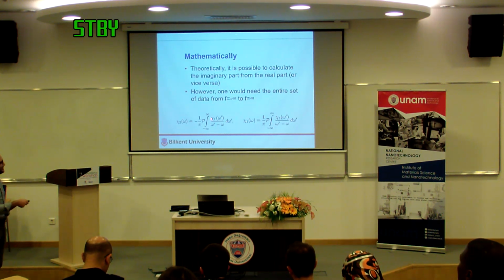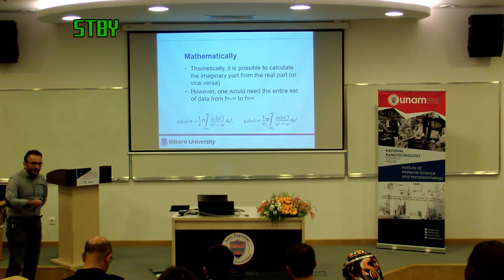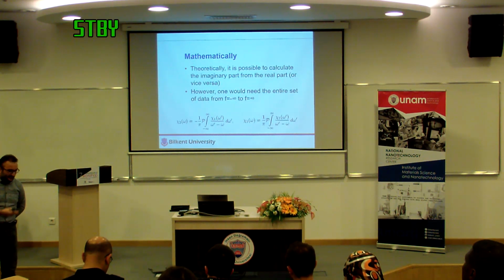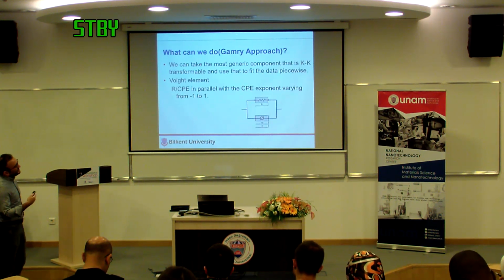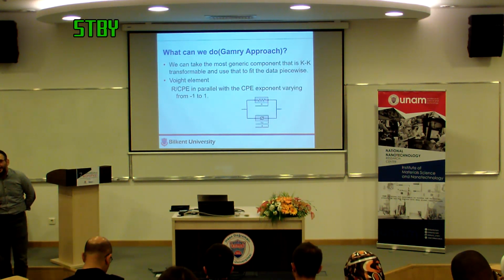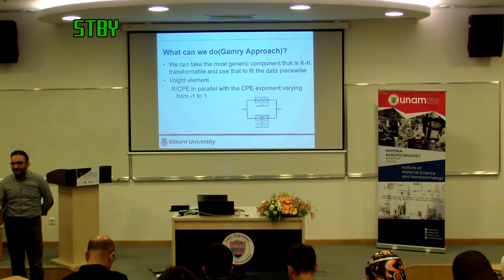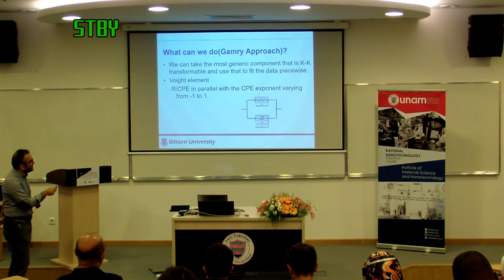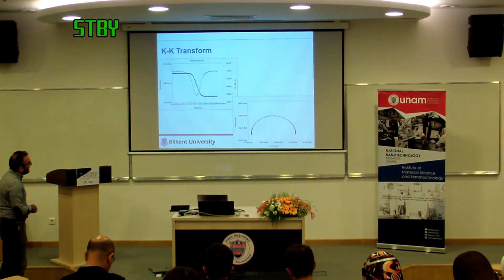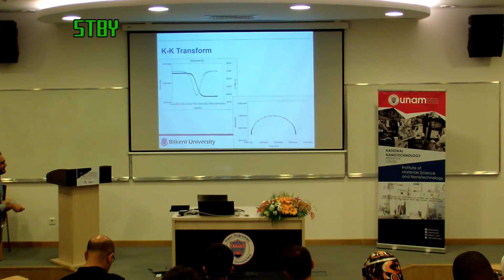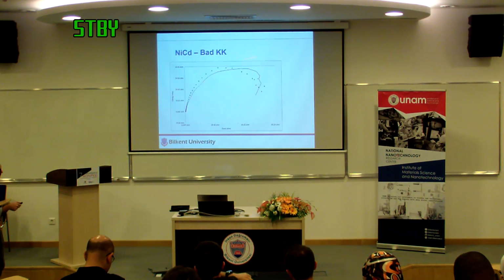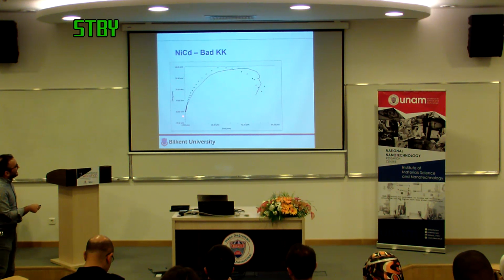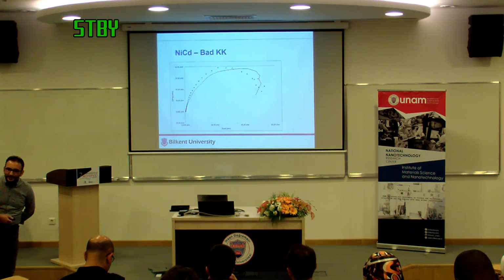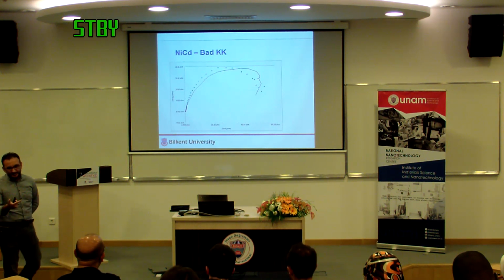The problem with doing this transform is you need the entire frequency set, going all the way to infinite frequency and minus infinity, because things are symmetric. So we use some mathematical trick to approximate it. We don't actually do the full transform, but we look into other methods of checking this. I'm not going to go into the detail of how this is done, but ultimately, when things work, they work. The Kramers-Kronig transform looks like this, and when things don't work, they really don't work. So this one right here is some data that I took, and it's clear that the Kramers-Kronig transform did not work. So this is either nonlinear, non-stable, or non-causal.